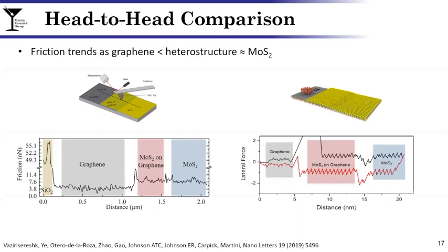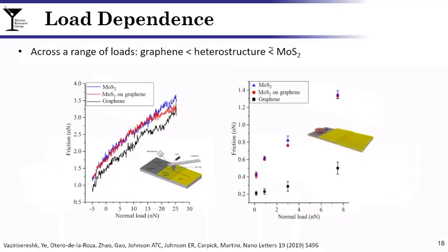This was repeated along multiple scan lines in the experiments and at many different loads. So what I'm showing you now, again, the left is the experiment, the right is the simulation, is the comparison of friction as a function of normal load between the MoS2, the graphene, and the heterostructure. And you can see here across all the loads, the MoS2 has higher friction than the graphene. And in some cases, you can see that within the error of either the experiments or the simulations, the heterostructure has slightly lower friction than the MoS2.